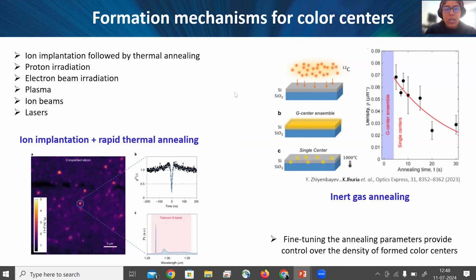Until 2020, whatever emission we were getting was basically coming from a cluster of these color centers inside silicon. So that's why it was difficult to use them directly as qubits. But in 2020, for the first time, it was reported that you can actually make them at single center level, meaning you can isolate this color center or point defect, and hence have a single photon as an emission.